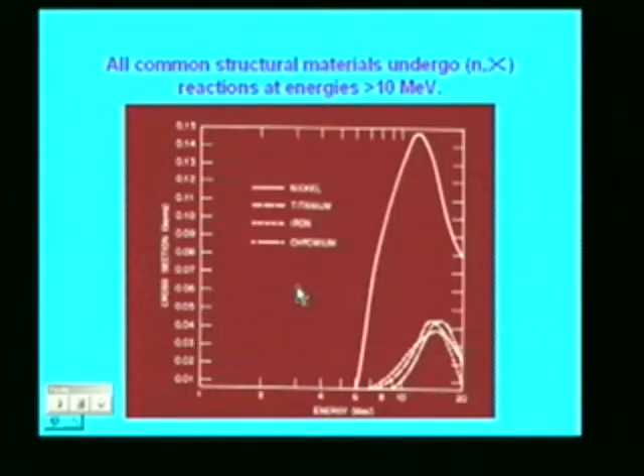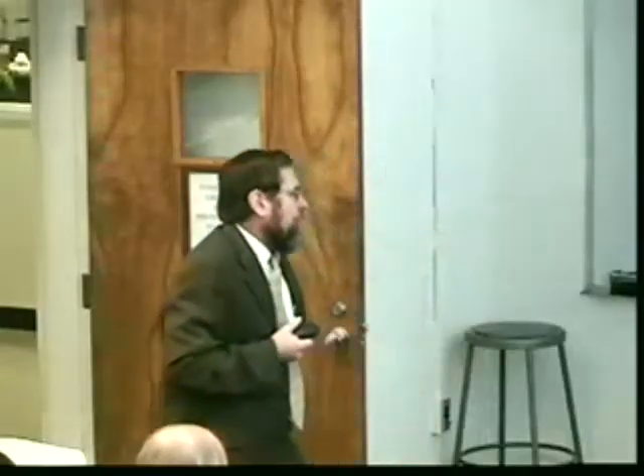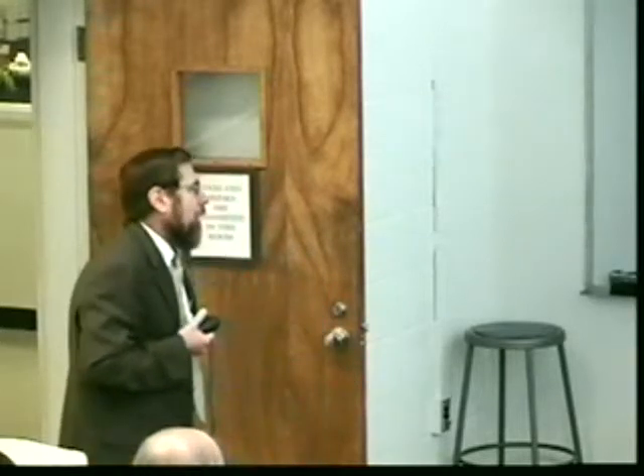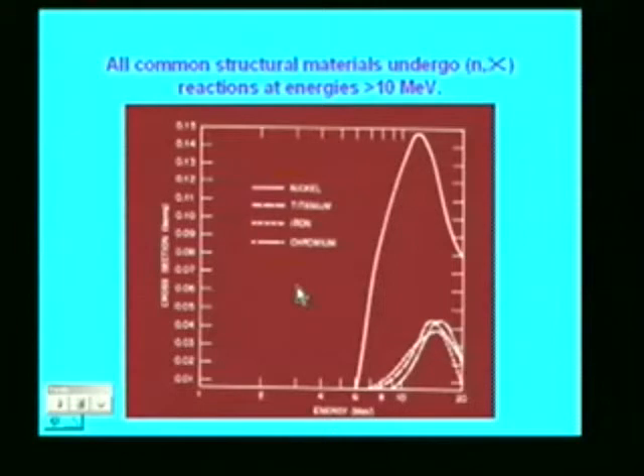Well, we talked about transmutations, and particularly n-alpha reactions in fusion reactors. And one way, you might say, to get around this problem is just to be very clever about choice of materials. But what I'm illustrating here is that if we look at the n-alpha cross-section for common structural materials, we find above about 10 MeV, they all have significant n-alpha cross-sections. Now you might say, well, let's stay away from nickel, that's a particularly bad one. But here, iron, chromium, titanium, and I could fill up that graph with a lot of other materials.